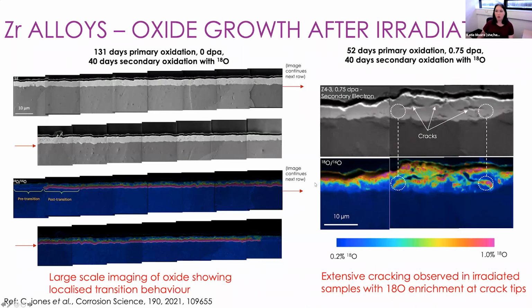So the real aim of Chris's thesis was to look at oxide growth during irradiation. What we have here is two different images with different levels of irradiation on them. On the left-hand side is where we started to move to try and image larger areas of a sample with the NanoSIMS. This is actually just one strip of oxide presented over two lines here. In this particular case, we had introduced oxygen 18 into the autoclave to look at where particular parts of the oxide were being particularly active in that time.